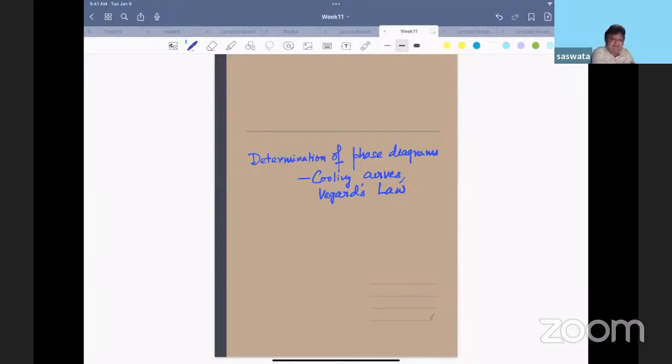So this is not a compound energy formalism. It's a very good question. It is not a compound energy formalism where I can actually look at vacancies or electrons. But here it is a much simpler model based on regular solution where we do not consider vacancies. However, if you want to consider vacancies, this is always possible. You can basically have like A, B, or C, D. Think of two sublattices where one sublattice is occupied.